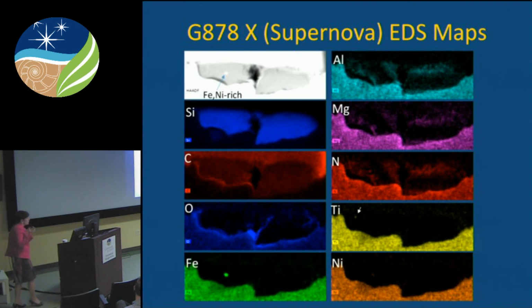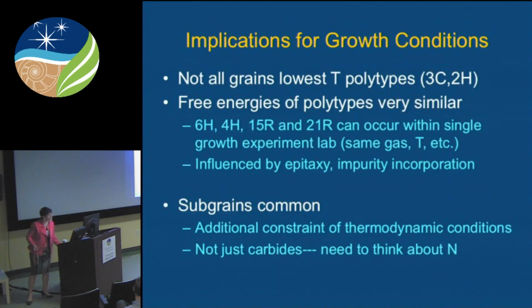That's because that magnesium is actually the decay product of the aluminum-26. So that's actually purely magnesium-26, magnesium mapped with the EDS spectrometer. The nitrogen also mostly spatially correlates with the aluminum, so it seems to be primarily in solid solution with the silicon carbide matrix.